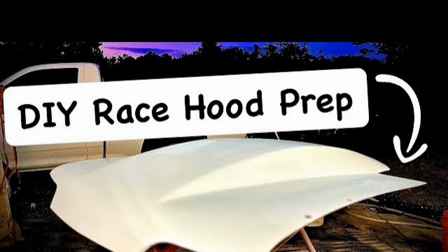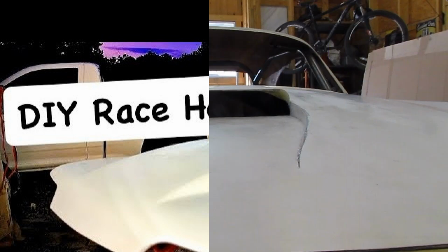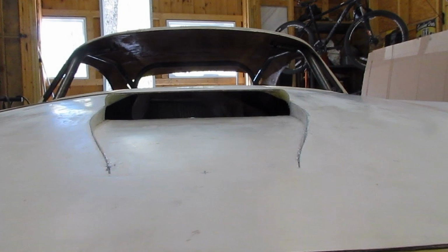With an ordinary polyester resin, it will be quite enough to apply 2 to 3 layers, and then leave the matrix for at least 24 hours at a temperature of 18-25 °C. During this time, the surface will dry, and all shrinkage processes will end.